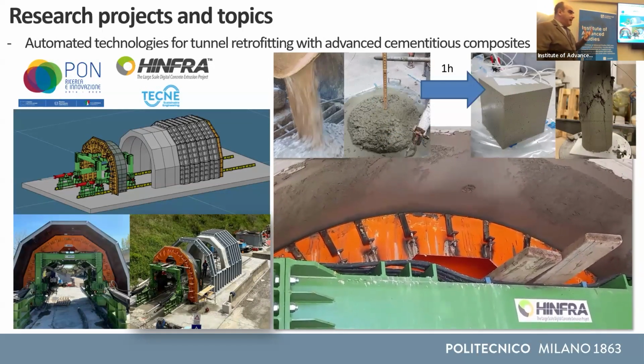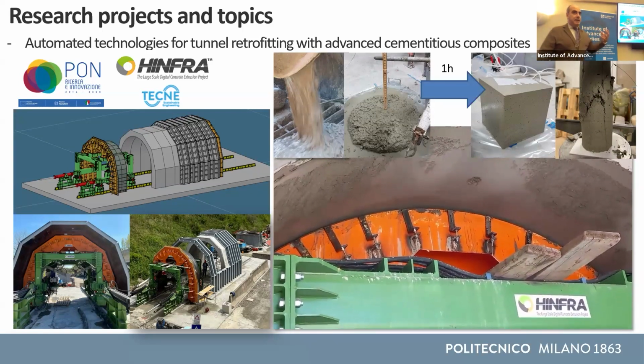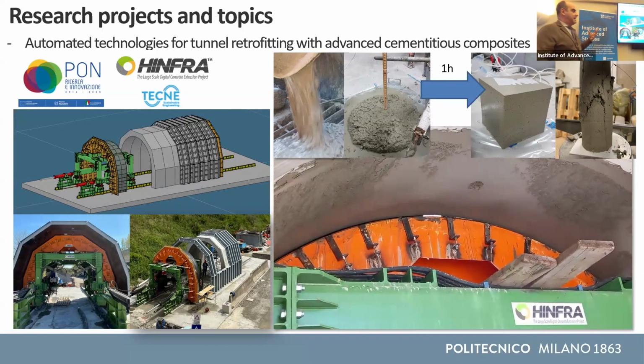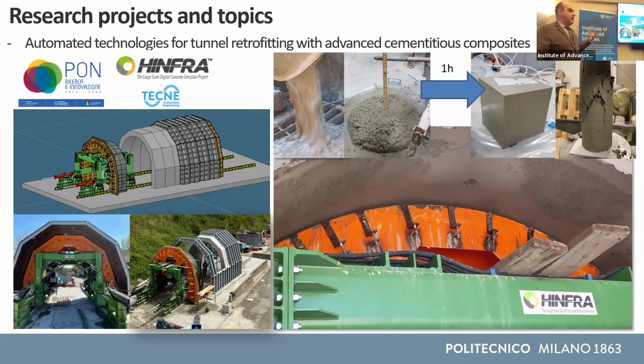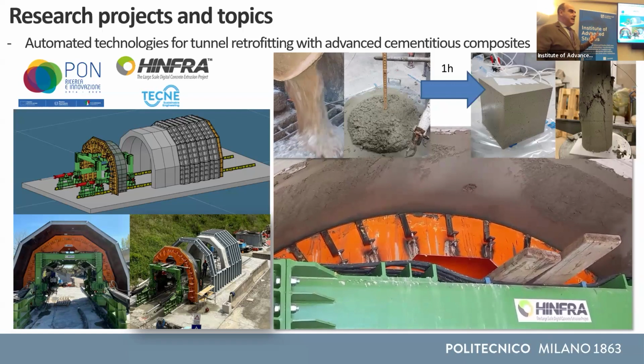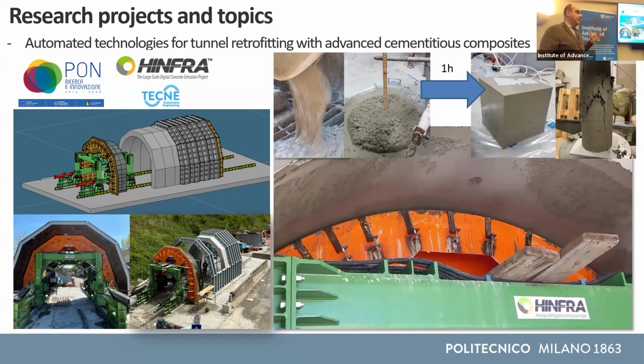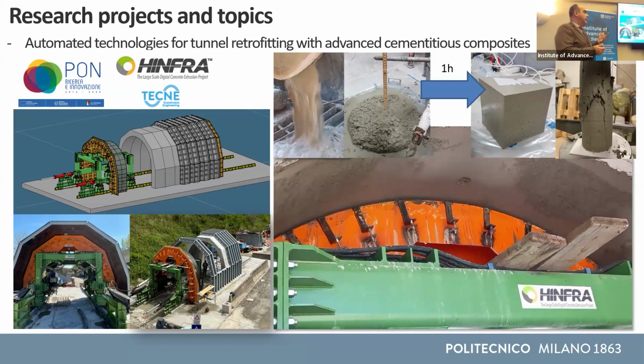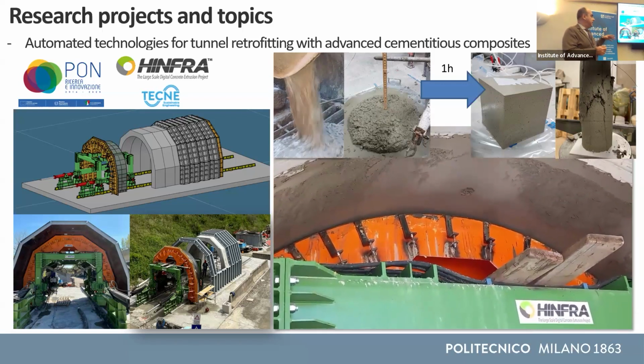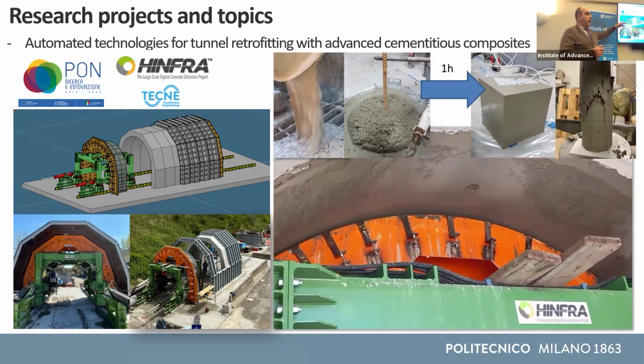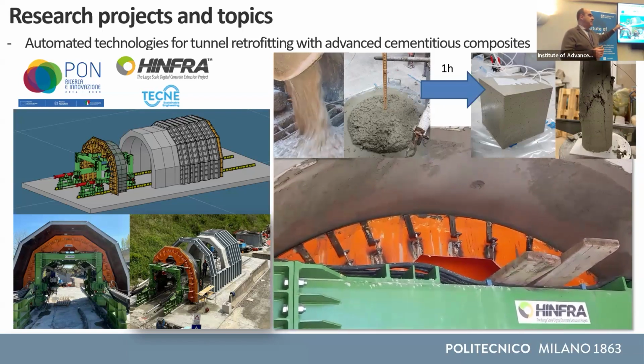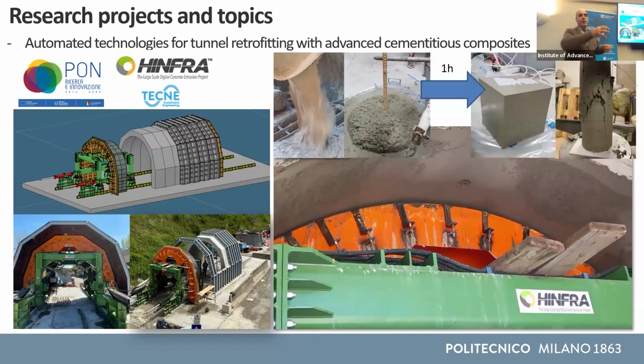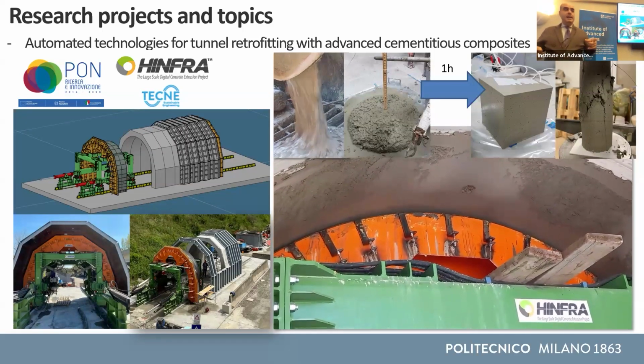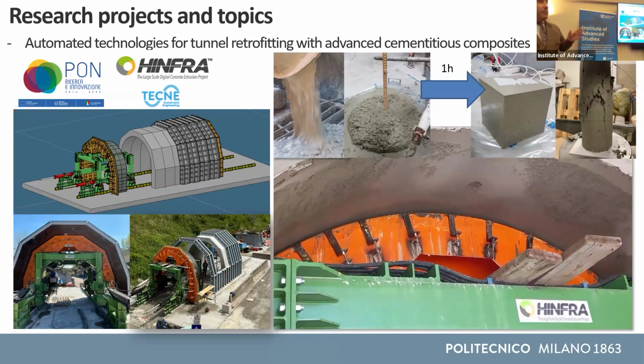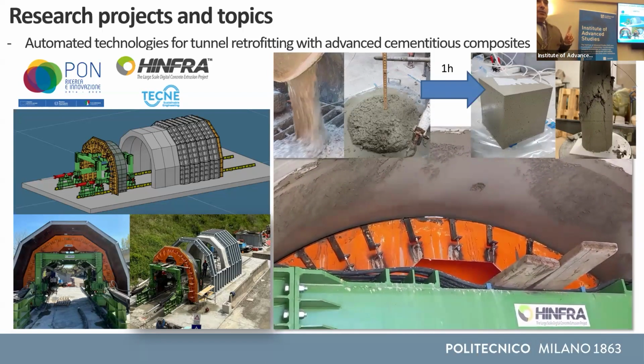From that knowledge, the knowledge of 3D printing material, which must exhibit fast setting, we went into this project. So the mix is like a 3D printing mix. It sets almost immediately, a little bit less than the 3D printing one, but this was used for tunnel retrofitting. There is this slip forming unit. You pump at time zero a self-compacting fiber reinforced concrete mix, and after 1 hour you are able to slip form. So the vault is able to withstand and develop a compressive strength of about 8 megapascal in 1 hour in order to be able to stand.